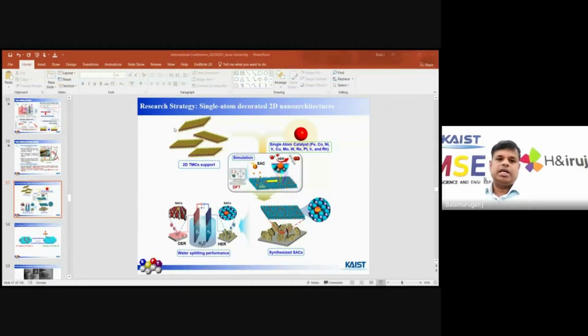You can see we took a transition metal chalcogenide substrate, and we use different types of single atom catalyst. Previously I discussed the graphitic network, but here I am using some transition metal chalcogenides like molybdenum sulfide, molybdenum selenide, or whatever transition chalcogenides. Why do we use molybdenum or tungsten based materials compared to other chalcogenides? Because molybdenum, tungsten, or some tin based materials give thinner layers. With a thinner substrate, like a thinner network, the single atoms easily anchor over the area. Another thing, thinner networks may enhance the active sites more than the thicker ones.